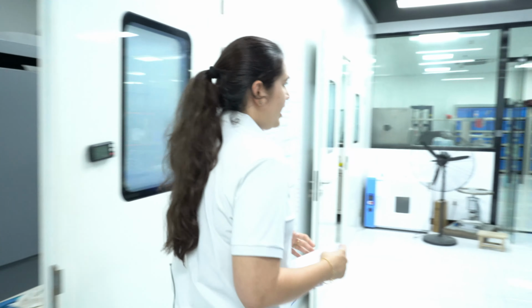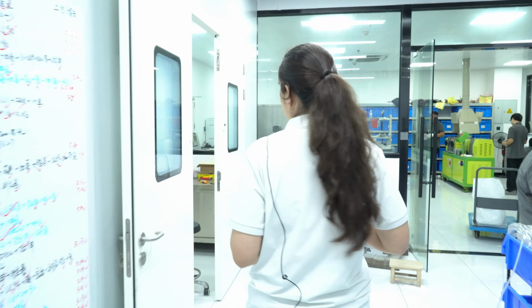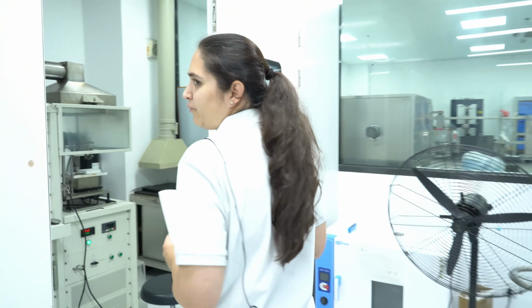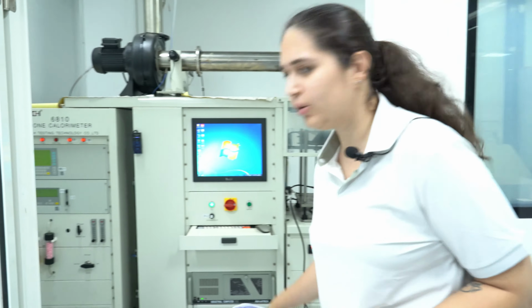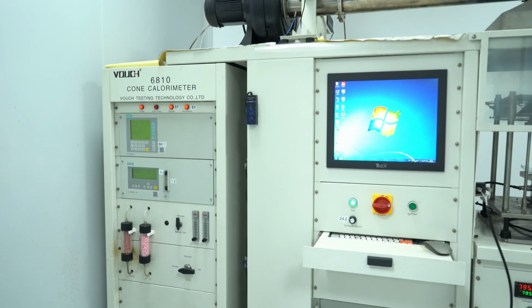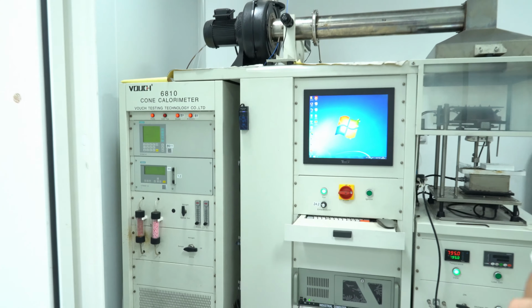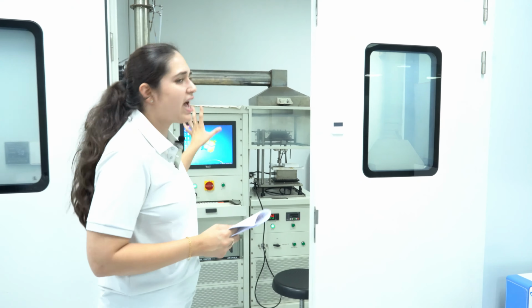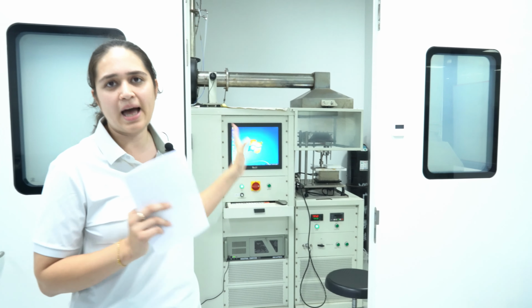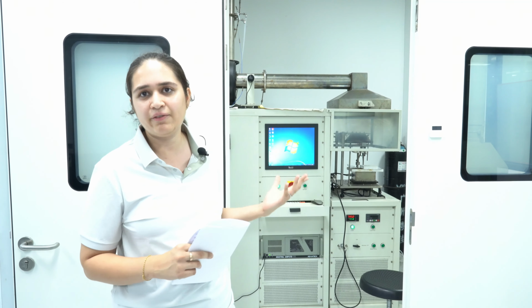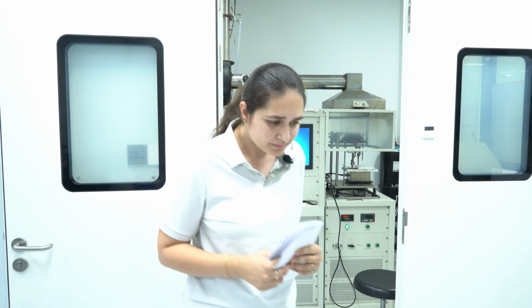And now at last I would like to show you the cone calorimeter. We are also equipped with a cone calorimeter in our lab. The cone calorimeter is one of the most advanced and accurate techniques to test the flame retardancy properties of our materials. With this machine we can get a whole variety of data, including heat release rate, total heat release, smoke production, CO production, CO2 production, and this machine is really reliable because we can test the samples on different parameters related to time, temperature, and also we can adjust the heat flux according to the requirement of customers.